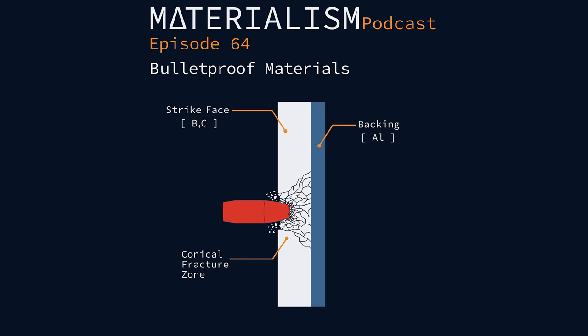Now, ceramics are strongest in compression. You don't want to use them in a tensile situation. They fracture quite easily. And so rather than fracture occurring at the surface where the bullet has struck, it actually starts from the back, at the interface between the bottom of the ceramic and the next plate, and it works its way towards the area of the impact. And so the bullet is not actually going to penetrate the armor until that crack and fracture has reached the impact site. And so you get something called dwell. Dwell basically just refers to the time during which the bullet is stopped from penetrating the ceramic.